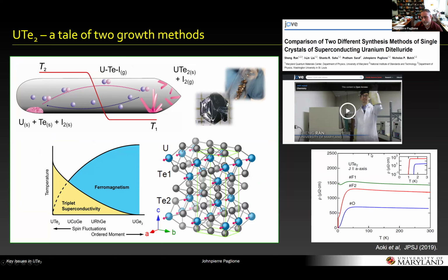it was already known, of course, from the discovery of the superconductivity that if you grow these crystals in slightly different ways, even with chemical vapor transport, even with the same furnace, same materials, you just change the temperature and you get different quality crystals. And so if you're interested, Sheng made a JoVE video article if you want to watch that. That's from several years ago, before the advent of flux growth crystals that superconduct. Back then he was comparing just flux growth crystals that did not superconduct to vapor transport crystals that did.